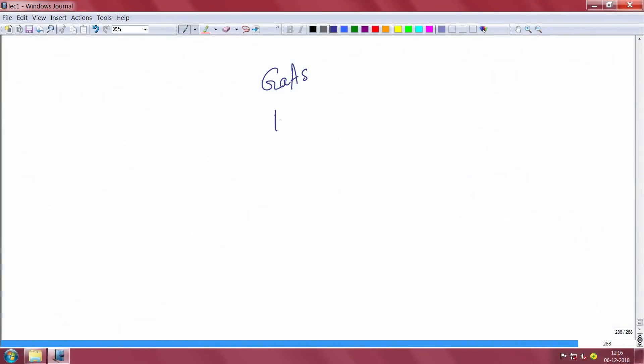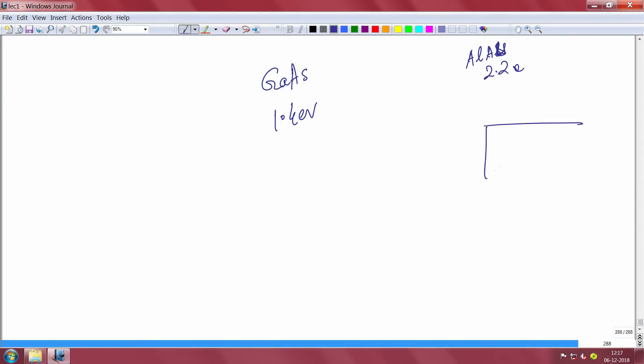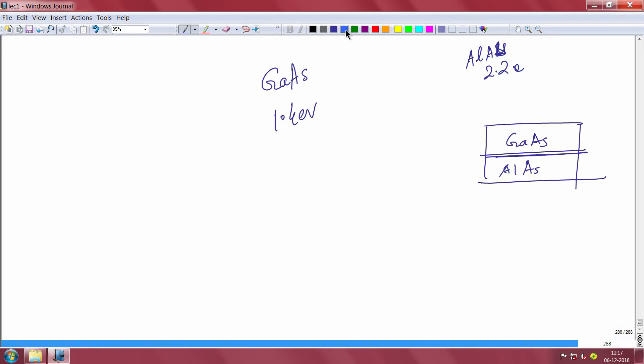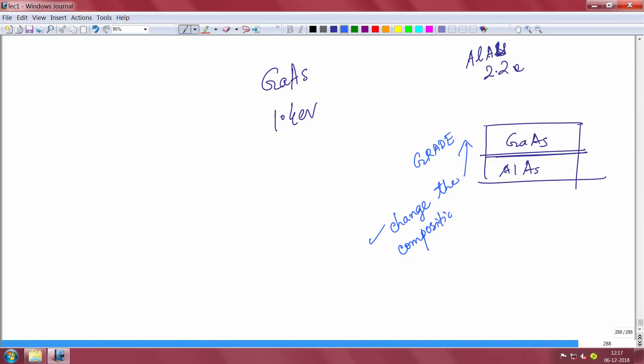Let us come to the whiteboard. What I am saying is that you have gallium arsenide with a band gap of 1.4 eV and aluminum arsenide with a band gap of 2.2 eV. If you make a heterojunction it is abrupt — like gallium arsenide and aluminum gallium arsenide — it is abruptly changing. But instead, what we can do is grade it: gradually change the composition of aluminum gallium arsenide rather than abruptly.